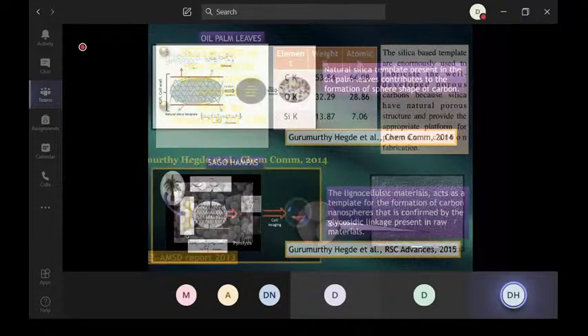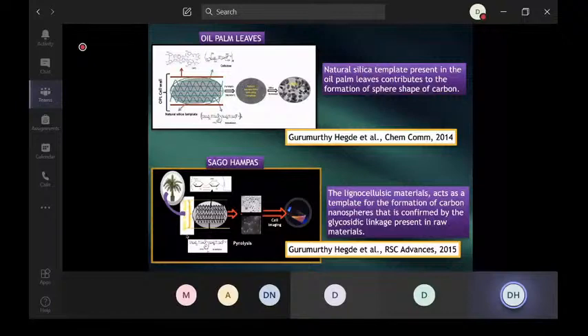Then, to our surprise, we did an experiment on oil palm leaves, and we explained that such kind of argumentation holds good, because this is a template approach. Then we did a similar experiment on sago hampas. We synthesized the nanoparticle. We got the porous structure, everything. But to our surprise, for sago hampas, this kind of template approach doesn't hold good, because their lignin content is less than 2% and silica content is less than 1%.